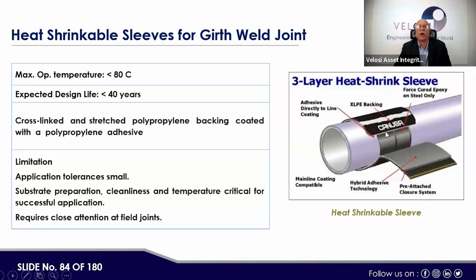So this is also one part of the three-layer polyethylene coating, because field joints have to be made by the heat shrinkable sleeves for the girth weld joints. Maximum operating temperature up to 80 degrees Celsius. Expected design life 40 years. Cross-linked and stretched polypropylene backing coated with a polypropylene adhesive. Limitation: application tolerance small. Substrate preparation, cleanliness, and temperature are critical for successful application. Require close attention at the field joints.